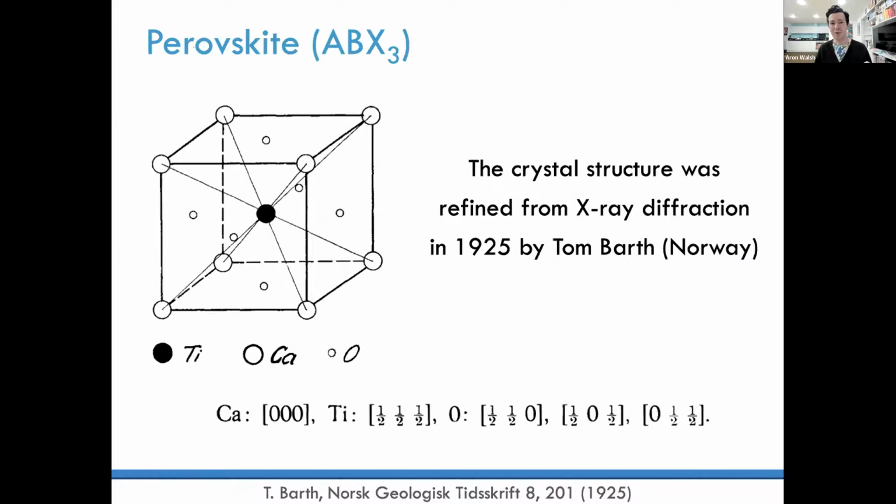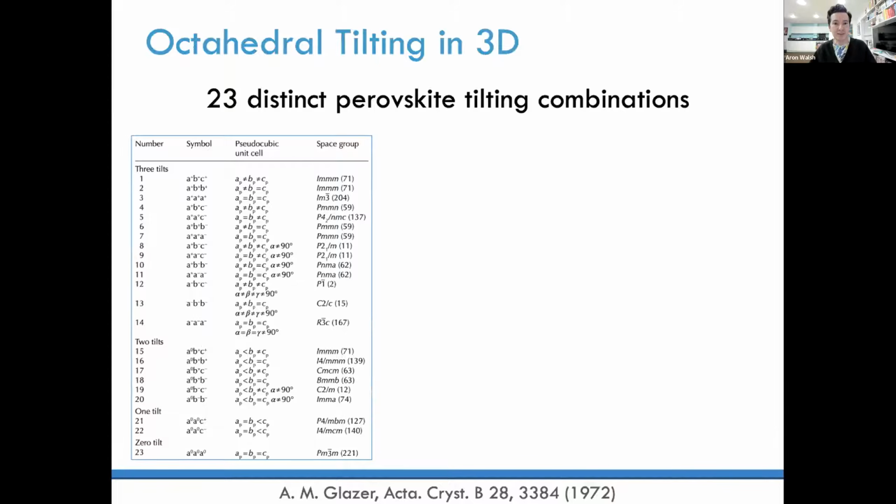And probably many of you, whether you like them or not, you've come across the perovskite structure at some stage. But the simple high symmetry prototype is relatively straightforward. It's a cubic structure, a primitive unit cell with five atoms in the basis. And the crystal structure was determined back in 1925 with the structure of the mineral form of calcium titanate. But the interesting thing about perovskites is not that cubic parent structure, it's all of the derived lower symmetry structures that can emerge from that.